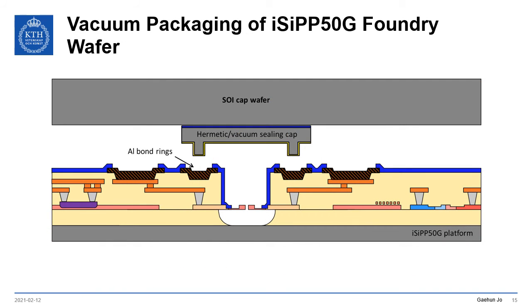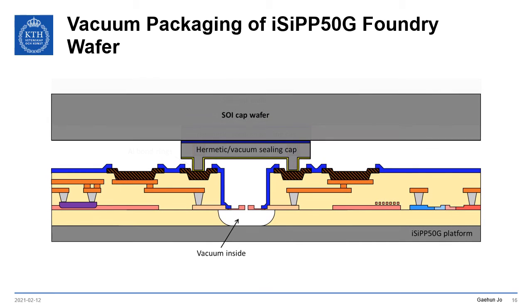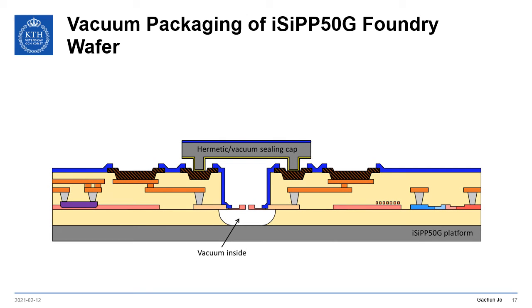For the vacuum packaging of the ISIPP50G foundry wafer, our approach is transfer bonding of thin silicon caps. The SOI cap wafer, which contains many sealing caps, is aligned to the photonic foundry wafer, and subsequently bonded inside a vacuum chamber to seal a vacuum inside the cavity. Next, the handle layer of the SOI cap wafer is removed, leaving only the individual thin sealing caps on top of all the photonic devices, as shown in the figure.